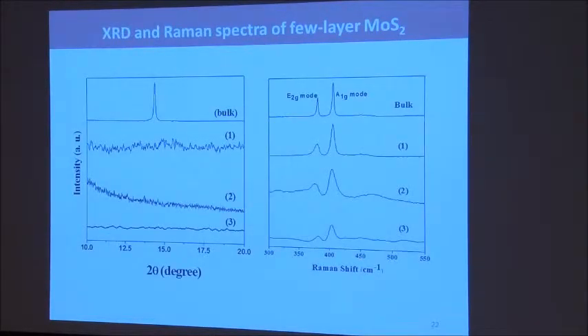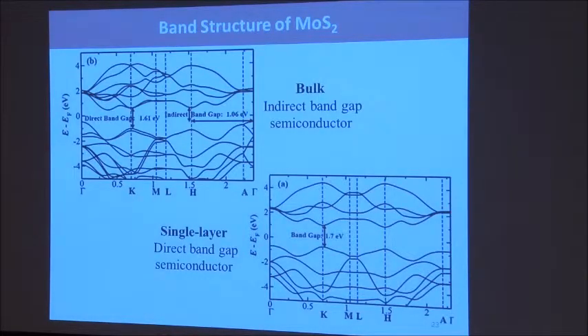A number of various chemical methods are available. Well, how do you know you have made it? You see there is a 002 reflection in the X-ray diffraction, and that immediately disappears as soon as you make a single layer or two-layer molybdenum sulfide. And then you can also study the electronic structure.